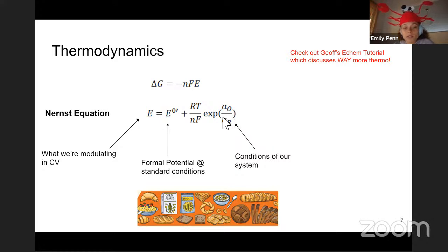For species dissolved in solution, we normally use the concentration of the species. But from this, we can determine the equilibrium potential for the reaction. And this E, the potential, is what we're modulating in CV. So as we're scanning over the potential range, we're modulating the free energy of the reaction, and this has an effect on the activities or the concentrations of our oxidized and reduced species near the electrode.